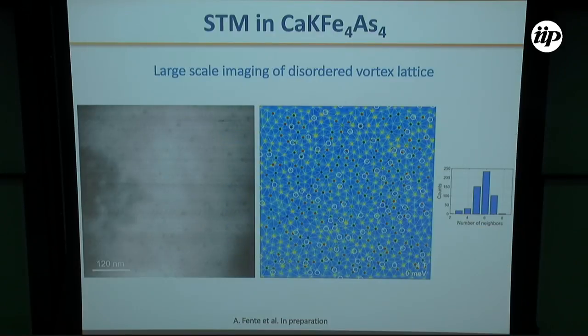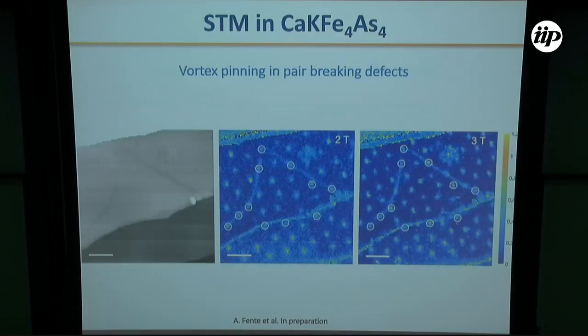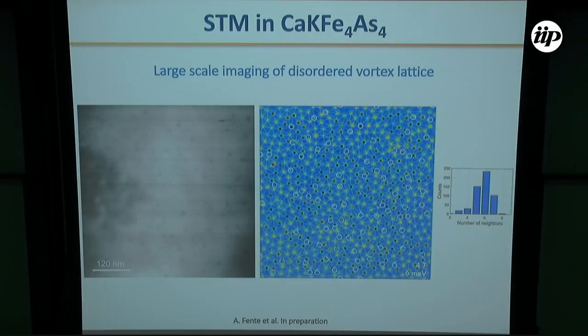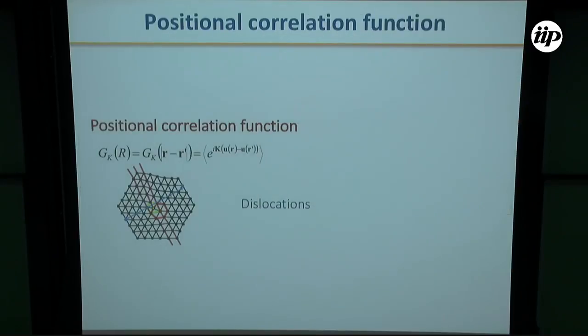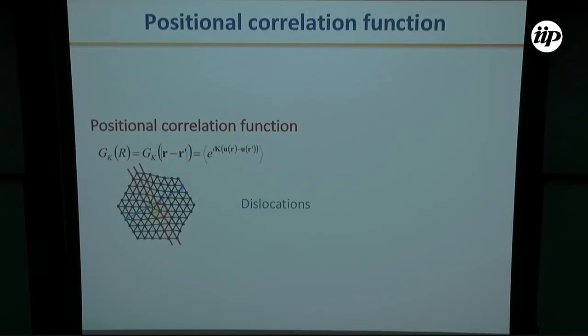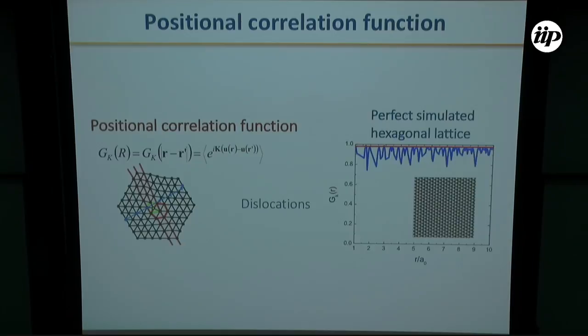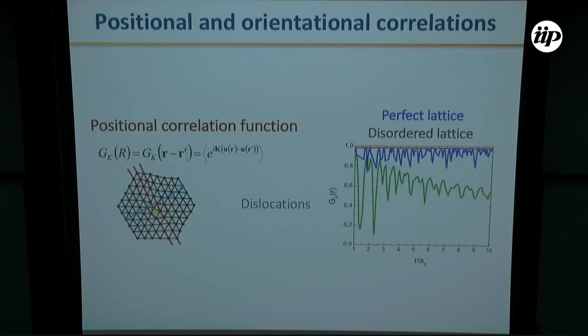We have also analyzed images where we don't have this individual pinning limit, but collective pinning, in a region where the disorder is more homogeneously distributed. And we have found a very disordered vortex lattice. To quantify the disorder in the vortex lattice, we have calculated the positional correlation function. Essentially, this function is constant and equal to 1, independent of the distance, for a perfect hexagonal lattice, and its value decays with the distance when we introduce some defects.